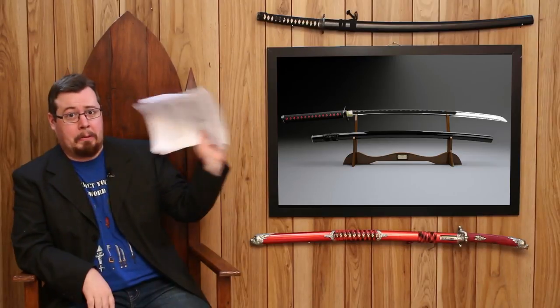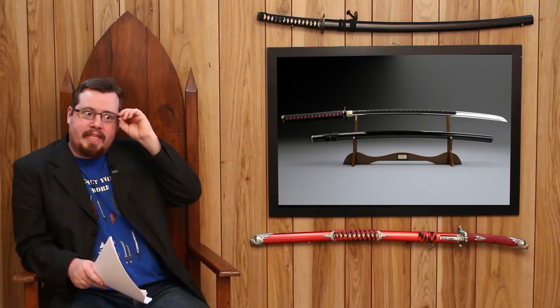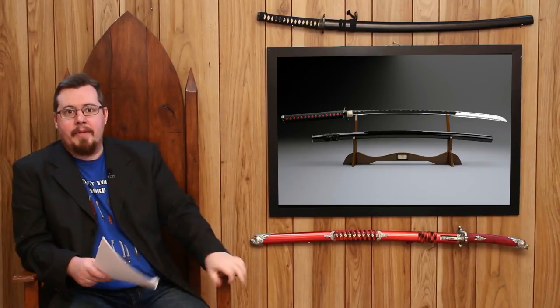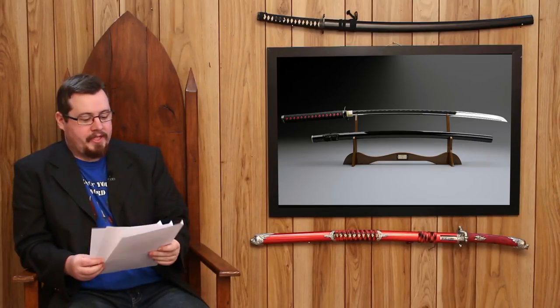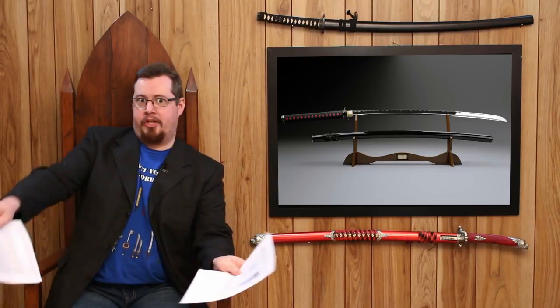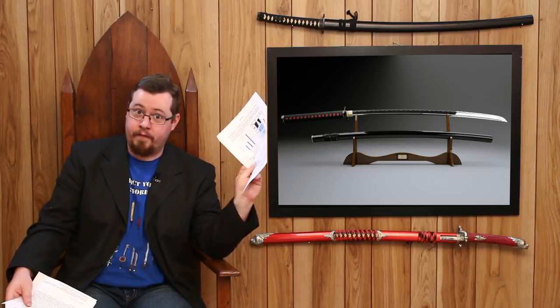Whoa! If you want the smoking gun in regards to the truth about the katana, most of it can be found right here! Remember that last point that they made? Most of the inclusions came from the iron sand that they were using. So if you wanted proof that if you get iron oxide sand and collect it in a traditional way, it's going to have lots of impurities in it still. Confirmed right here. Also, that a traditional katana still has a lot of impurities or slag in it, okay?